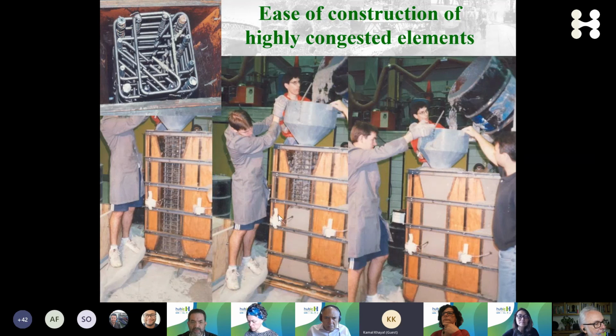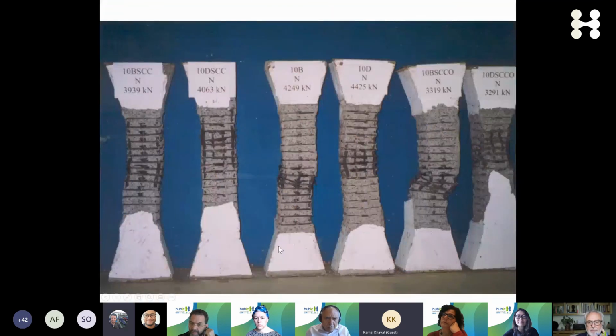And in the lab here, we tried to reproduce some of these structural elements in seismic areas. This is about one-third of a cubic meter. Using SCC, it takes about 30 seconds to fill this. You fill it up like water. And if you were to use high slump concrete and do it layer by layer, internal vibration, it takes about 15 minutes versus 30 seconds. And the structural performance is very similar.